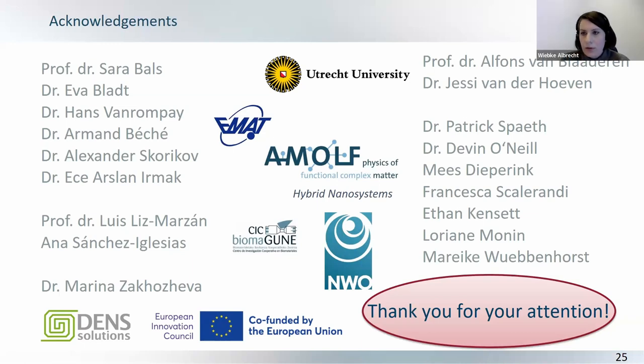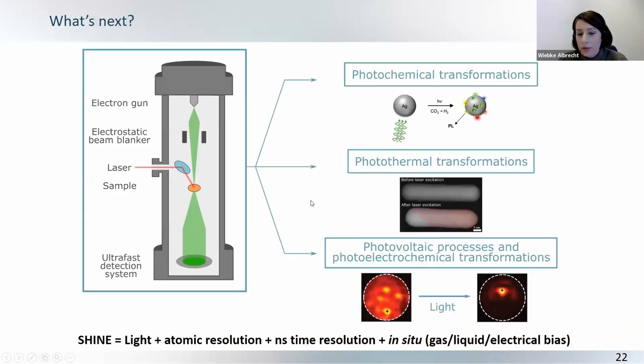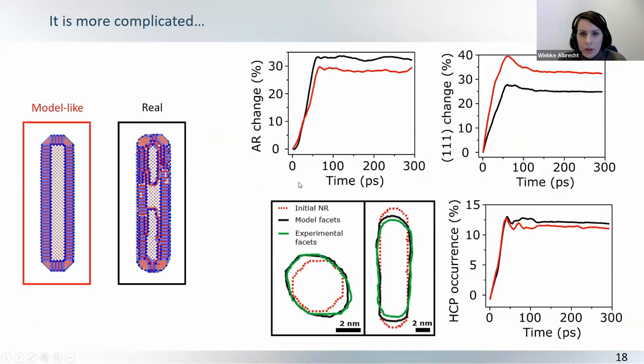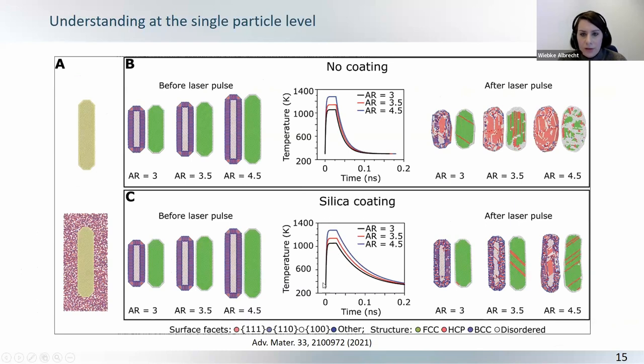Yeah. So, this was always now in a medium, right? And if you're in liquid, these experiments were actually in glycerol. So, this plays an important role, the cooling. For example, here, you can see that there's a tiny difference in cooling, or in heat dissipation. For silica, it goes just a bit slower than just in pure glycerol. But that gives the particle a bit more time, and it's somewhat elevated, more elevated temperature to restructure a bit more into its preferred configuration, basically. So, it plays an important role in that sense.